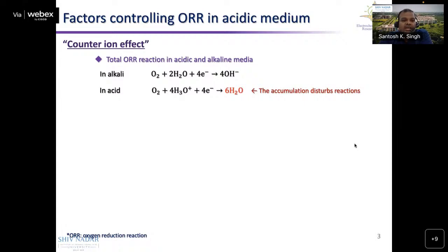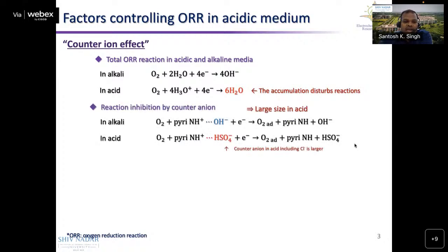However, in the acidic medium, what happens? Basically, water is produced at the cathodic side, and this water gets accumulated at the active sites. Along with the water, most of the ions, like sulfate ions or chlorate ions, also get accumulated, and they block the active sites in the pyridinic nitrogen containing catalyst. So this is how this mechanism works here.